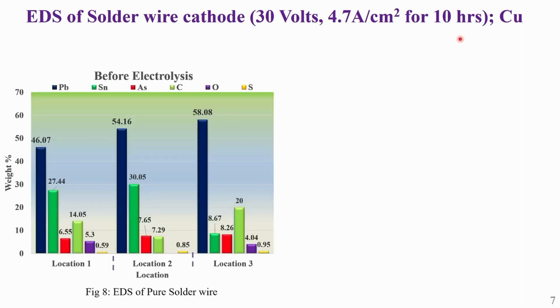Let us look at one more EDS result for solder alloy. We do electrolysis at 30 volt with 4.7 ampere per centimeter square for 10 hours. The left figure tells the EDS results of pure solder. The pure solder contains mostly lead, tin and arsenic. Here the dark blue bar represents lead, the dark green bar shows tin, and arsenic is in red color.